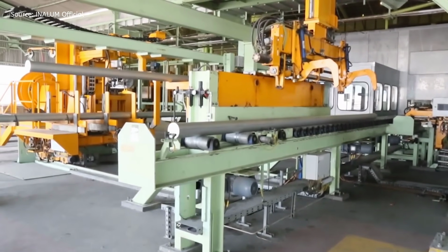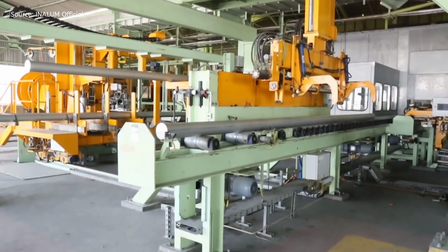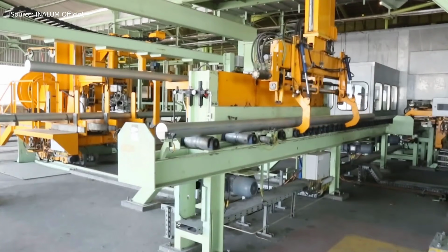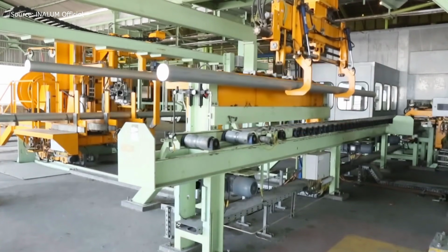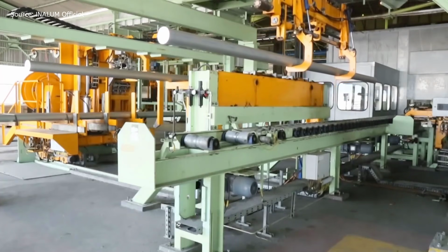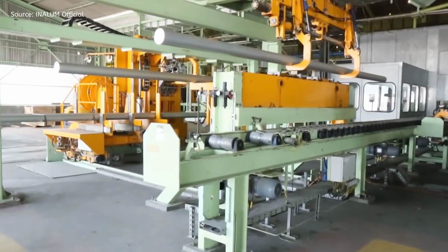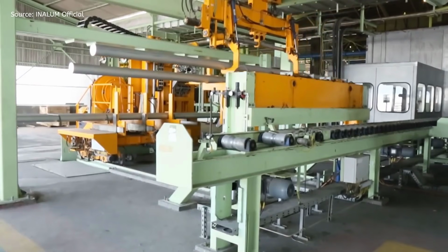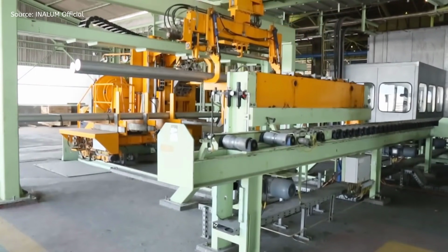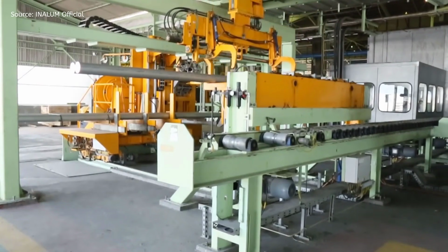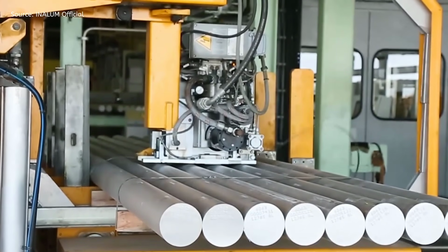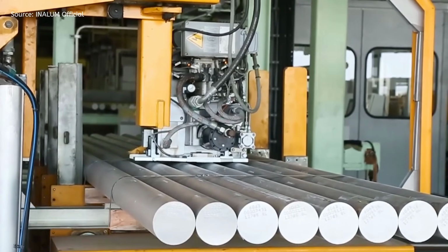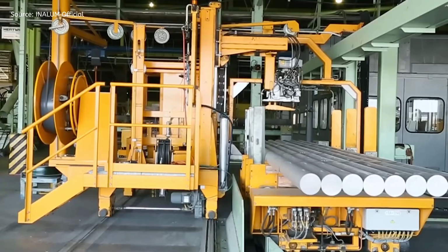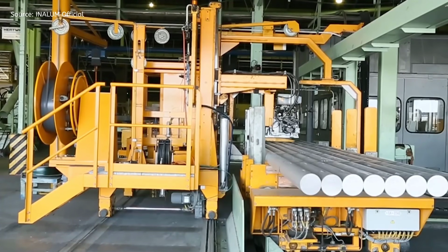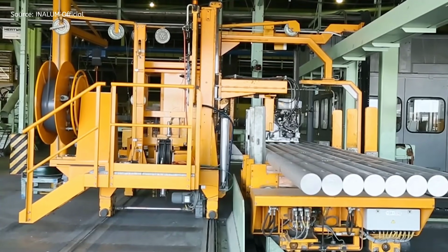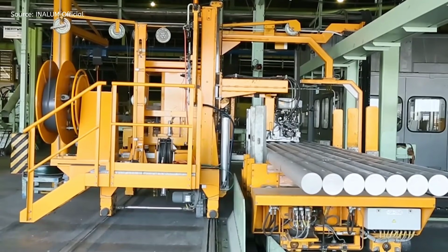Before casting, the molten aluminum undergoes degassing with argon gas to eliminate hydrogen and passes through filters to remove residual impurities. The cast billets are subjected to ultrasonic inspections to detect surface and internal defects. Following inspection, billets undergo a homogenization process to enhance metallurgical properties and mechanical strength. The final billets are cut to standard or customer-specified lengths, bundled, and stored for shipment. Quality control is maintained through accredited laboratories equipped with advanced instruments to ensure compliance with international standards.